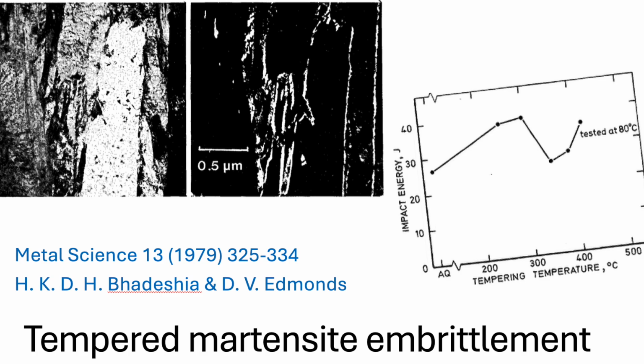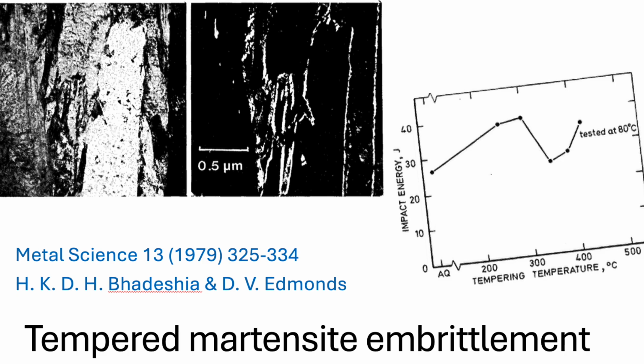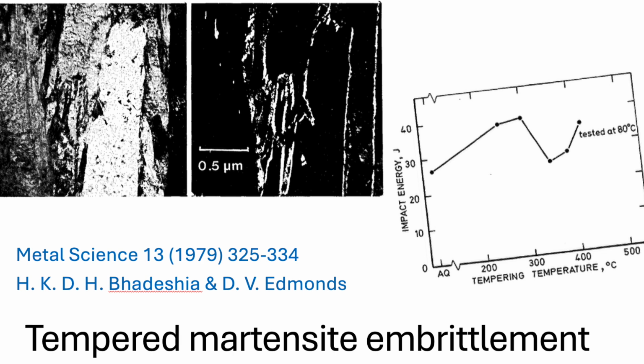Right, so now we shift our focus to fractography, basically, analyzing the surface of the broken steel sample. Looking closely at the broken pieces, specimens that were tempered right in that TME danger zone, especially when they were tested under stress at cold temperatures, exhibited classic cleavage fracture. Cleavage fracture, that's the really brittle kind, right? Where the crystal structure basically splits cleanly along specific crystallographic planes, defines brittleness.